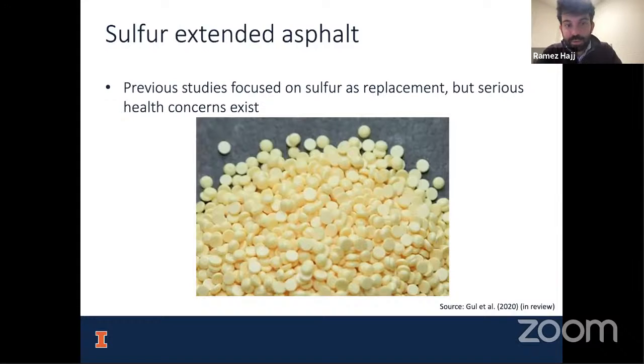Previous studies did focus on sulfur as a replacement, but, and this is from the worker safety perspective, we have to take into consideration the health concerns with sulfur, which means that we're typically using 150 Celsius for mixing asphalt. We cannot use 150 Celsius if we're mixing sulfur into asphalt because it emits too many hazardous chemicals.